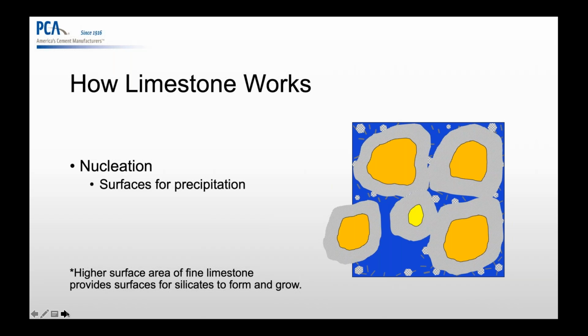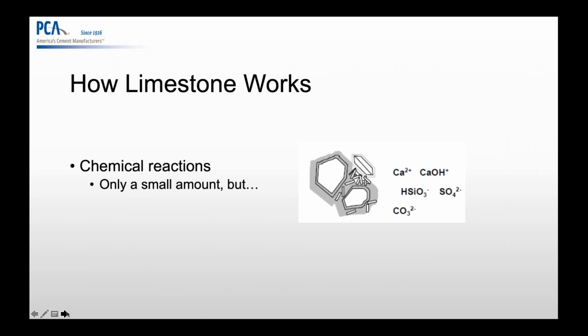In addition to that, there's more surface area for the silicates to grow on the limestone particles, so there's a promotion of nucleation, meaning that the silicates will form on the particle, and the CSH, the calcium silicate hydrate, which is the basis of the glue in the paste. That's what you want. You want some CSH to be formed. The limestone allows the formation of those silicates to promote strength. Again, limestone is an inert material, meaning that it doesn't create much chemical reaction, or only very small amounts. But this may be due to the fineness of the material.